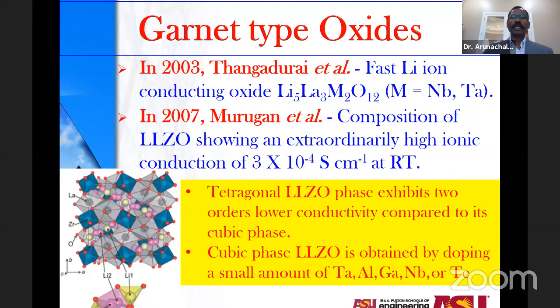So the next one is obviously the garnet type oxide. It was in 2003 when Dr. Thangadurai, who is in Calgary right now, reported a garnet-like structure, which is again based on lithium lanthanum, niobium, or tantalum-based oxides. That was one of the very good materials reported 17 years ago, and then in 2007, Dr. Murugan, who is in Pondicherry University now, reported lithium lanthanum zirconium oxide. That was probably the one that opened the door for research on this garnet structure for lithium battery solid-state electrolytes. When reported, it was up to 3 × 10⁻⁴ per centimeter at room temperature.